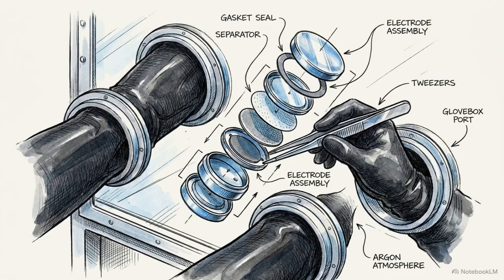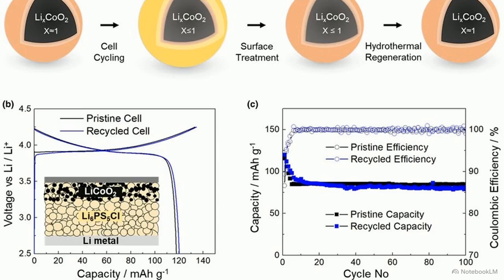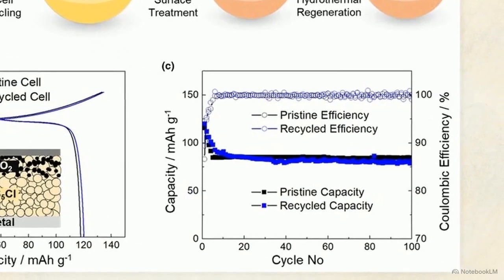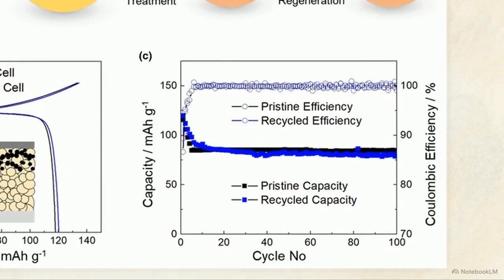To validate the entire process, researchers built a new cell using only these recycled materials. These performance charts plot the voltage profiles and cycle retention of a pristine battery against our fully recycled battery. The lines overlap almost perfectly. The recycled cell achieves nearly identical first cycle capacities and maintains a coulombic efficiency of over 99.9%.